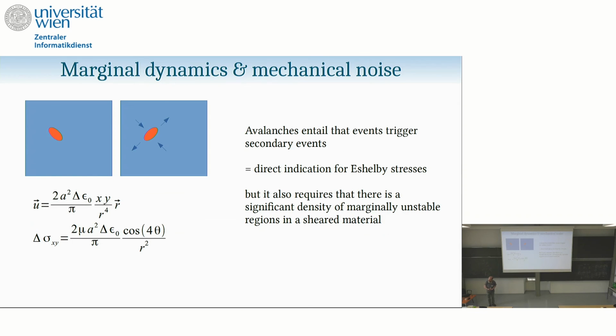The point is that when we see avalanches, it means that avalanches, of course, are not single Eshelby events. They are cascades of Eshelby events, of shear transformations. And this is really consistent with the idea that when you shear your system, at some point there is a region which yields. Now, when this region yields, it increases the stress along the horizontal and along the vertical, and reduces stress in the other direction. So now imagine that farther away, you have another region which is very borderline, very close to instability. This first event occurring can push the other region beyond its instability and trigger a secondary event.